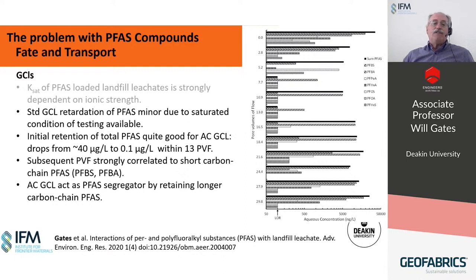If we modify the GCLs with organic carbon additives, such as activated carbon, we do observe some retardation of the breakthrough for the longer chain PFASs. We see a drop in the first few pore volumes of flow. However, if we look at the total PFAS loading, it increases again. And largely that's associated with the shorter carbon chain PFAS molecules dominating the transport in the higher pore volume flow measurements.